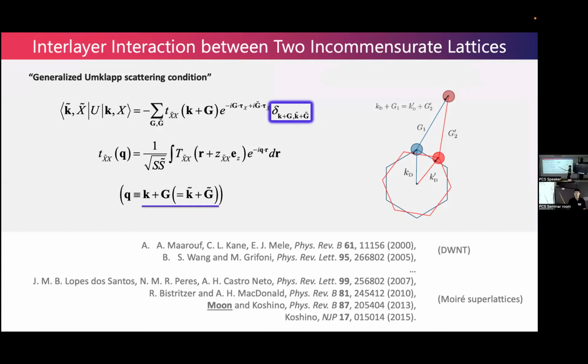The interaction between 2 lattices is written in this Hamiltonian. So K states in layer 1 interact with K tilde states in layer 2 with the interaction strength determined by the Fourier transform of the interlayer hopping integral. And also, it happens when K and K tilde match some momentum conservation condition. This is called the generalized Umklapp scattering condition. It has been extensively used in double-wall nanotubes even before the discovery of moiré superlattices, and it's now very popular in this system.